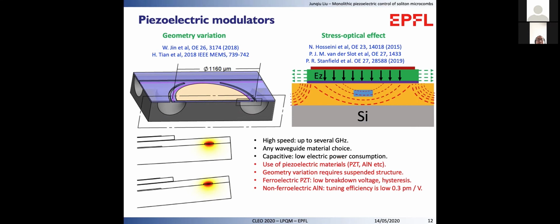The disadvantages are, first, this scheme is limited to only piezoelectric materials as modulators, which include PZT or aluminum nitride. The geometry variation requires a suspended structure. Also, ferroelectric PZT has low breakdown voltage and hysteresis of the tuning, while the non-ferroelectric aluminum nitride has very low tuning efficiency, which is about 0.3 picometer per volt. The non-ferroelectric aluminum nitride modulator is the material that we choose in our work.